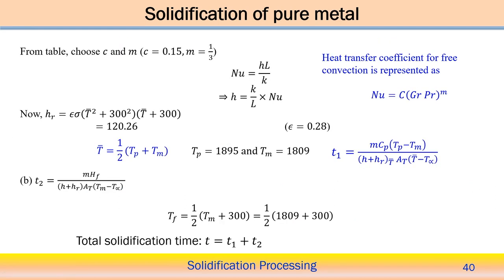Now from standard tabulated data, we can find the C and the constant terms. C equal to 0.15, m equal to 1 by 3. Because we are using this relation, the heat transfer coefficient for free convection is represented like that: Nusselt number equal to C into Grashof number and Prandtl number to the power m. So C is 0.15, m equal to 1 by 3. This we can take from the standard table, and once we get the Nusselt number, because Grashof number and Prandtl number we have already calculated, we will get some numerical value for the Nusselt number. Once we get this value, the Nusselt number equals H L by K. So from here H can be calculated, K by L into Nusselt number. So this is the way to calculate the value of H.